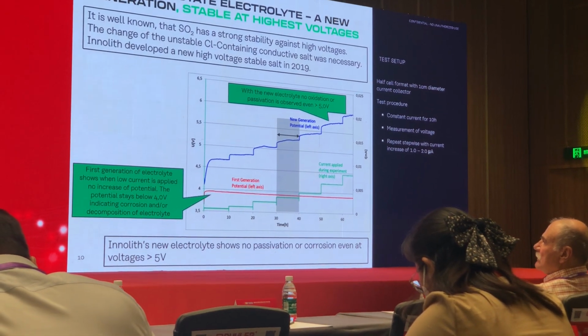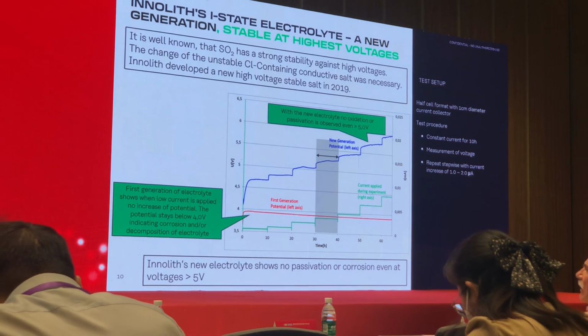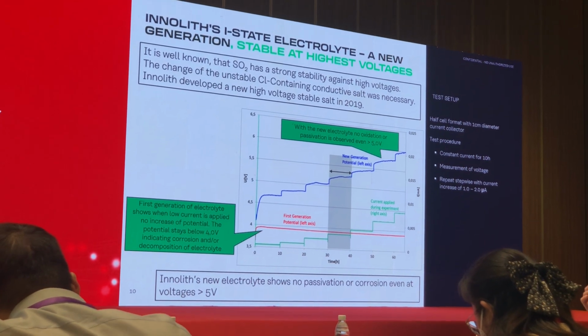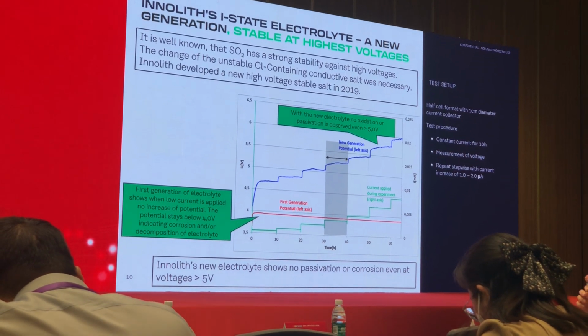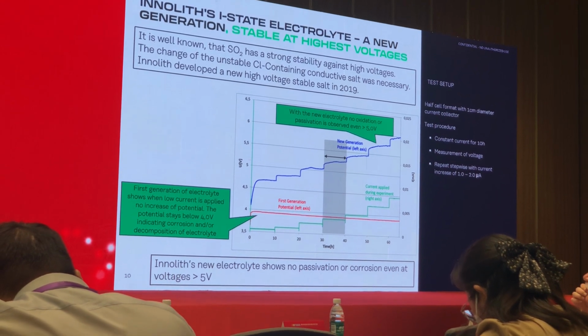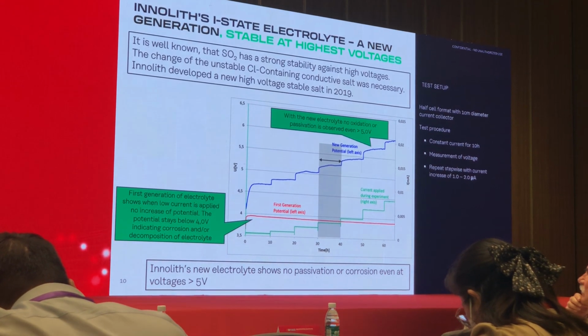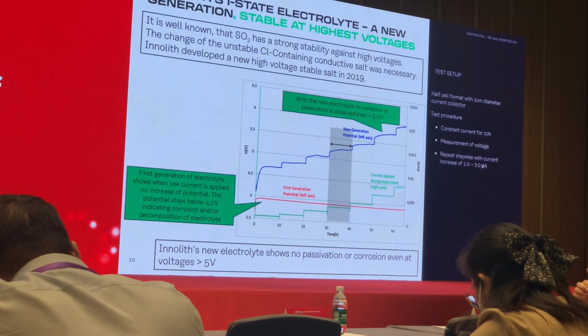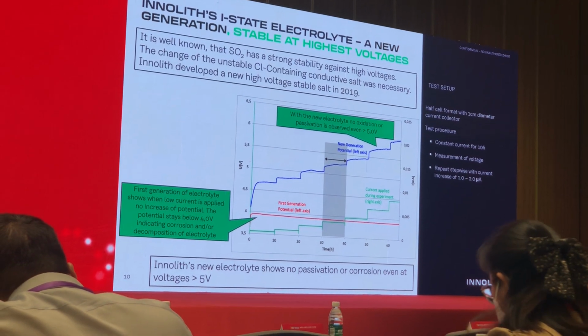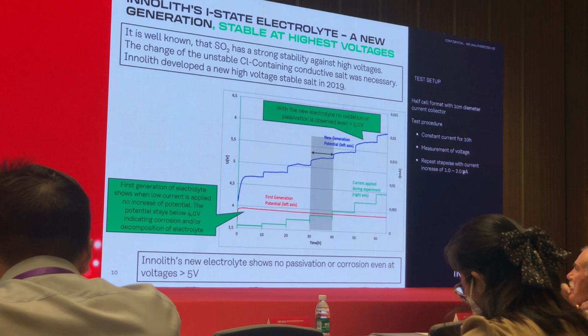And with our new generation of electrolyte, we have seen that even by increasing stepwise, the current potential was also increased but stays stable until we reach the limit of the testing device, which was 6 volts. This was our first important milestone in the development.